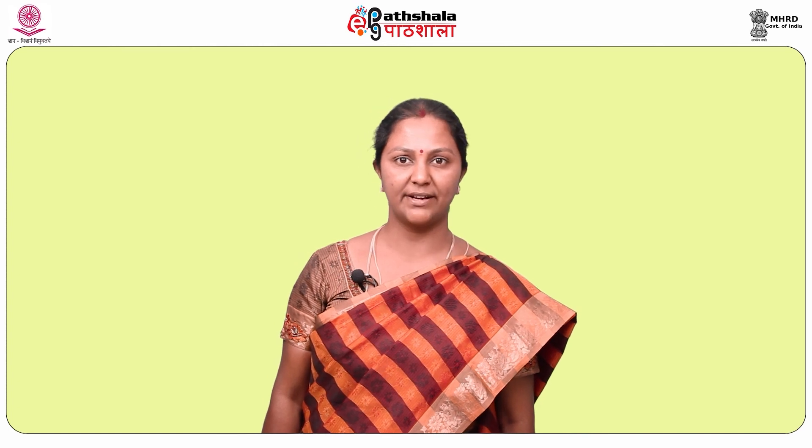Shearing: sheep are sheared usually in spring, once a year. Most sheep are still sheared by hand, though new technologies use computers and sensitive robot-controlled arms for clipping. Grading and sorting: grading is the breaking up of fleece based on overall quality, as high quality does not always mean high durability. Cleaning and scouring: raw or greased wool contains dirt, sand, grease and dried sweat. To remove these contaminants, the wool is scoured in a series of alkaline baths containing water, soap and soda ash or a similar alkali. Then the wool is treated with oil to increase manageability.